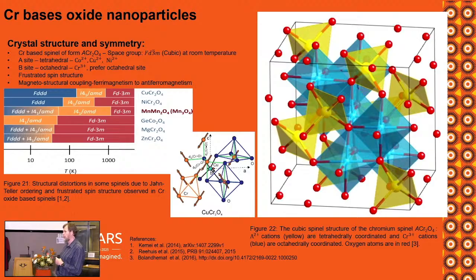But what's the difference now here? The difference here is that if we look at the spin structures, if I take one of these chromes in there, and I start looking at its nearest neighbor, and we start looking at the magnetism, the spin orientation. In chrome, we know they align outer corners in one direction, the inner one in the opposite, to give you antiferromagnetism. Here, these spins actually do not know what they must do. Must I act ferromagnetically? Must I act antiferromagnetically? And it's sums. So what happens in these systems is you then get sometimes a combination of magnetism.